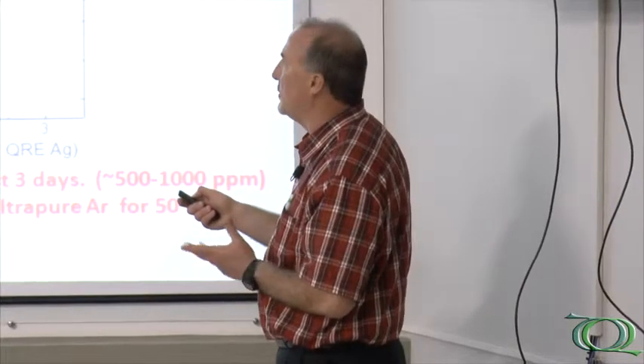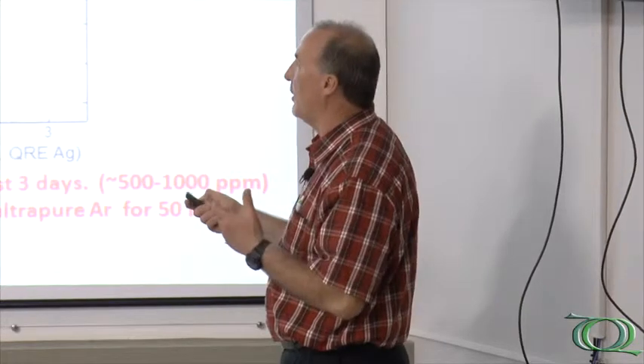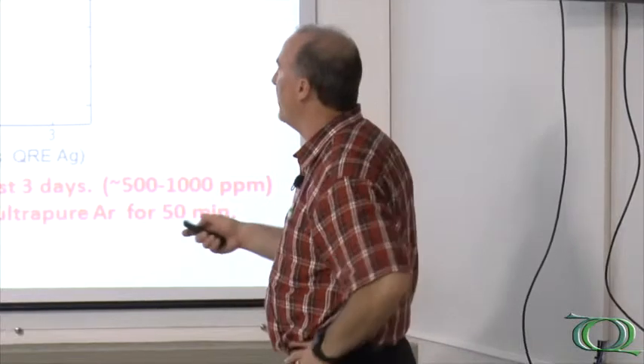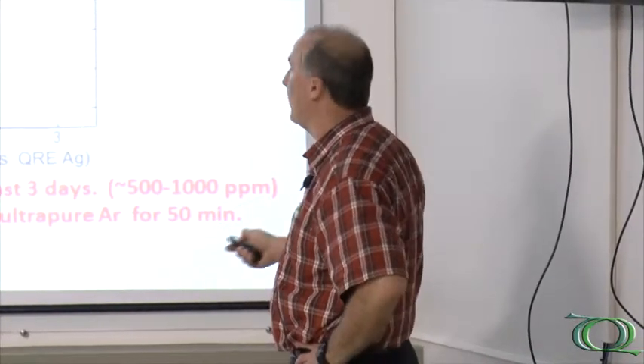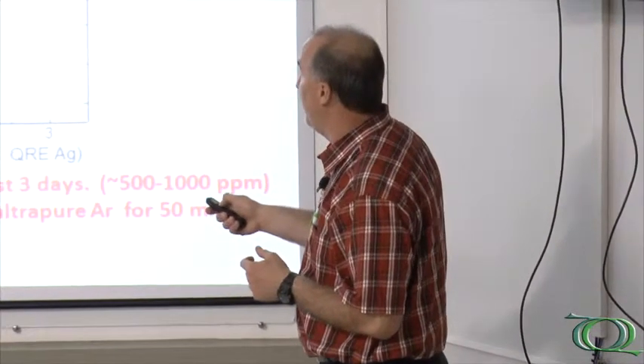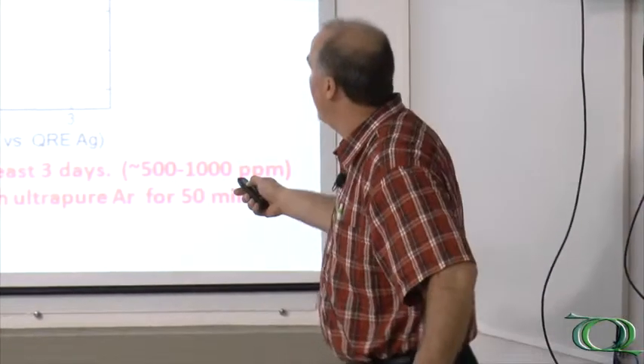We're showing two curves from two different purification processes: a traditional vacuum drying method and a sweeping method where we heat the liquid and purge with high-purity argon to more quickly displace the water. The black curve is for a TAC electrode — the electrochemical window is roughly six to seven volts, very nice for capacitor applications. The peak shown is the water oxidation peak. With the traditional method, several hundred parts per million of water are still present; with the sweeping method, less than 10 parts per million remains. So TAC materials have utility not only in aqueous systems but also in organic systems and ionic liquids.